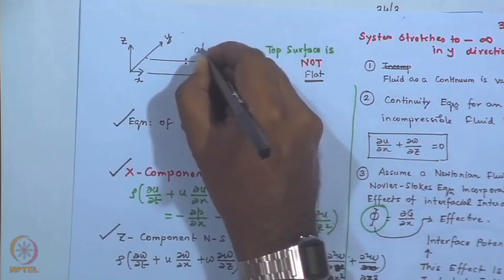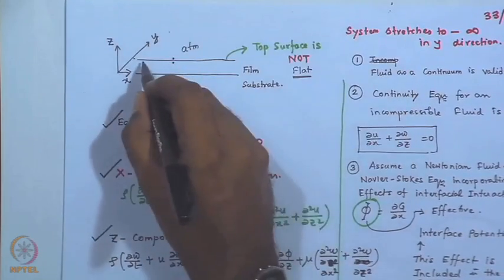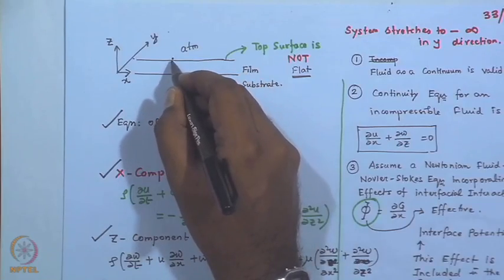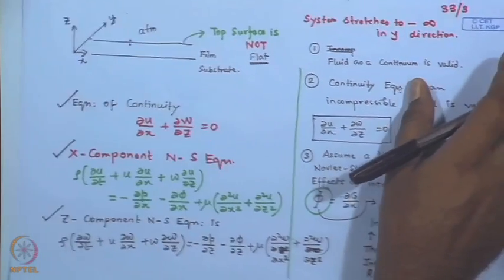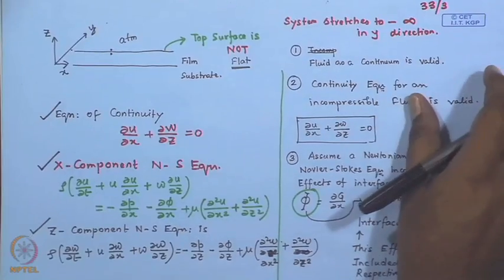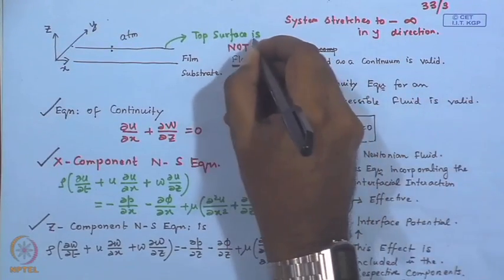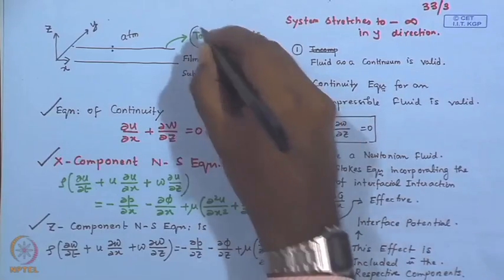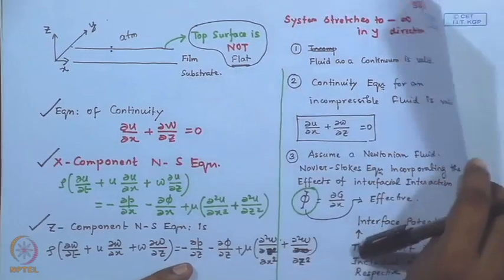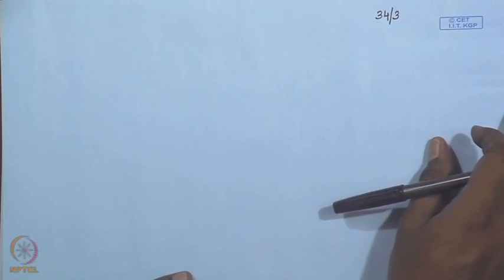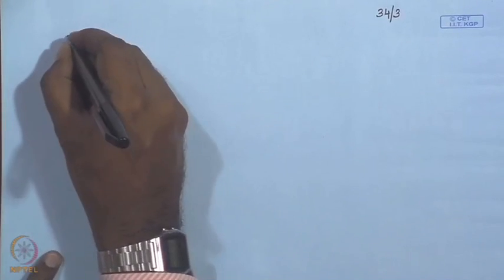at the outside and inside of the film. So, if this is exposed to atmosphere, you can't say that the entire film surface, the first layer inside the liquid layer, is at P atmosphere. Instead, you have spatial variation of Laplace pressure because of the curvature effect or the non-flatness of the film surface. Okay. So, consequently the Young-Laplace equation is valid on the surface. And the other thing, we assume that we regard these undulations to be axisymmetric. Okay. So, the surface undulations